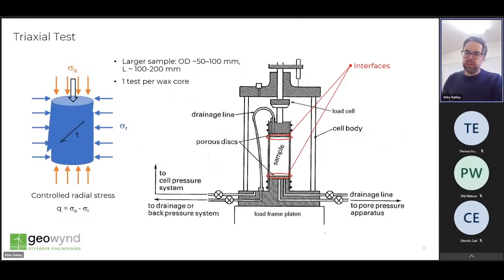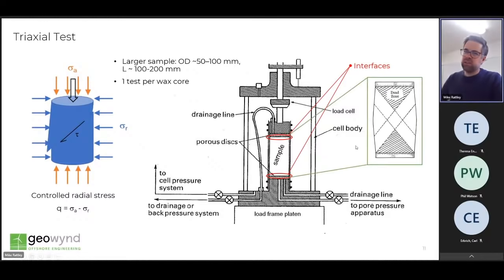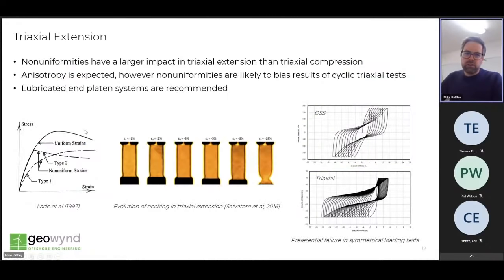The specimen arrangement in the triaxial apparatus also includes interfaces of the sample, as indicated in the loading platens, and these also create non-uniformities of the stresses and strains within the specimen, these so-called dead zones. Now, these non-uniformities themselves can be particularly important for cyclic loading since they impact on the extension condition of the test more significantly than in compression, leading to sometimes significant under-evaluation of extension strength due to the onset of necking. And necking is a process of localization, which is illustrated on the slide here.